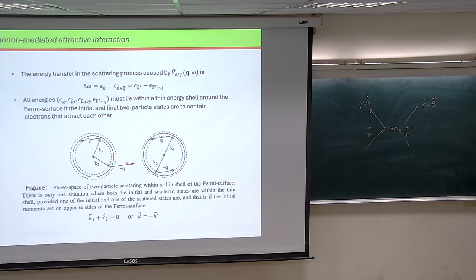Because you will go into the region in which the potential becomes repulsive, not attractive. It's just going away from it. So the only way you can guarantee that both of them will remain with momentum close to the Fermi surface is if they have opposite momenta, like here. So here one has K1, the other has the opposite, minus K1, which is K2, and if you zoom in on K here and minus K here, you see that they are still in the vicinity of the Fermi contour. So these are the electrons that are going to pair and form this phase. This is the condition then: the momenta must be opposite. Any question?